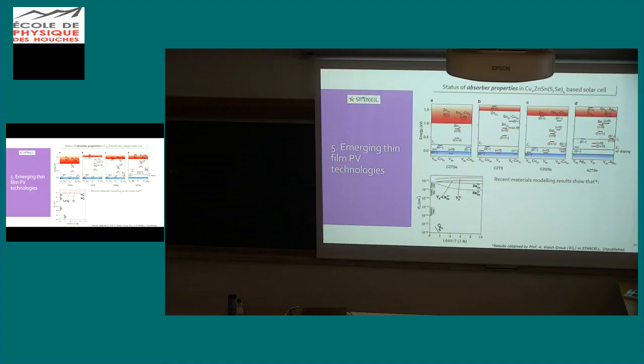But in the Starcell project, the biggest project on this material in Europe, the biggest initiative, very recently and just at the end of the project, the group of Aron Walsh that was included in Starcell proposed that tin-related defects can be at the origin of all these wrong properties of kesterite. Basically because the tin-related anti-site defects introduce deep defects that are recombination traps. So we need to avoid this kind of defects.